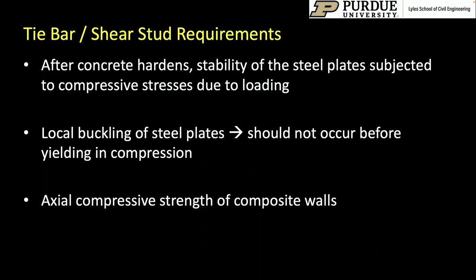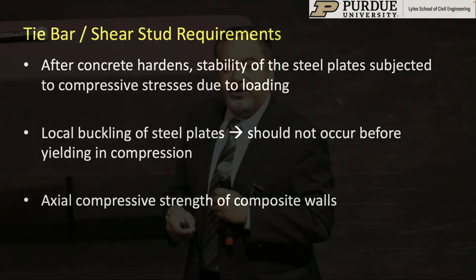And the stability of the steel plates, when it is subjected to compressive stress, is governed by the local buckling that occurs in between the ties or shear studs after the concrete has been hardened. So the local buckling of the steel plates should not occur before yielding occurs in compression. So we decided that from a design perspective, we're going to make sure that these steel plates are compact or non-slender, which means that they will yield first and then local buckling will occur in compression. This research also led to the equations for calculating the axial compressive strength of the composite walls.